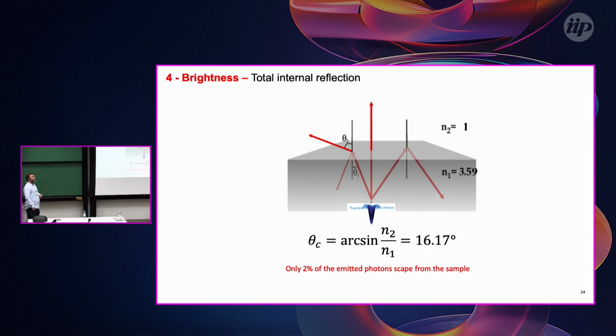Okay, the last thing that we check is the brightness. This is still an important field where people are trying to develop new kinds of cavities, because you want to extract more photons from these gallium arsenide quantum dots. Because of the refractive index of the materials that we use, gallium arsenide and aluminum gallium arsenide, only 2% of the photons emitted from the gallium arsenide quantum dots will be collected on the objective outside of the sample. And the rest, 98%, will be lost by total internal reflection.